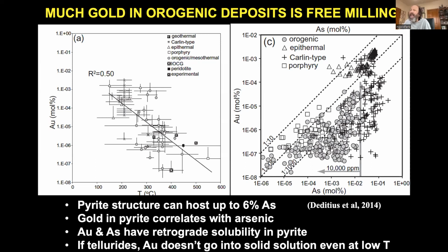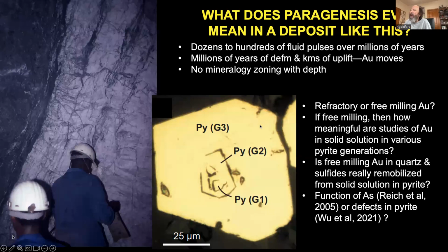So you may have a little gold in solid solution in pyrite, but most of your gold is going to be free gold. It can be small nanoparticles you may not see, but it's still free. And most of your arsenic is present as arsenopyrite. And so again, if we look at the amount of arsenic and gold in pyrite, in epithermal and Carlin deposits, it's high, but solid solution in orogenic gold deposits is low. So when people study pyrite grains, which we know form from many events of sulfide and pyrite forming, zoning in pyrite during all these hydrothermal events, and they start trying to make studies of solid solution gold and where the gold came that you see as free gold, that is meaningless because most of this solid solution gold in this pyrite is the waste that goes to the mill.